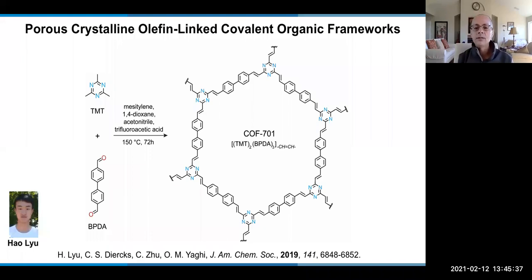This is a very important COF because it uses an unfunctionalized olefin to make an extended structure. So this COF is olefin linked, and it's entirely made from carbon-carbon bonds or carbon-nitrogen bonds. And these are very strong bonds. The reason we target this material is that we wanted to make a very stable, thermally and chemically stable structure. But you see here, we're using mesitylene and dioxane, and this student added acetonitrile, and it turns out he needed to use trifluoroacetic acid as a catalyst. So all of this is a result of many, many reactions in studying the conditions under which such a structure could be crystallized. So this is the X-ray powder diffraction.